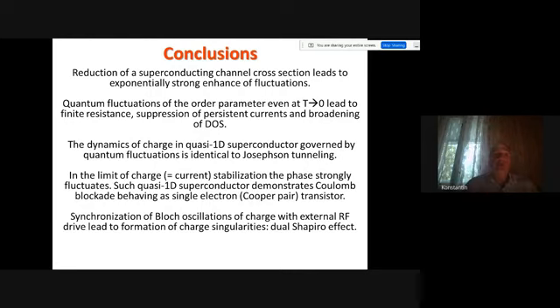So I'm now coming to the conclusions. What I wanted to tell you is that reduction of a superconducting cross-section turns it into a quasi-one-dimensional regime. And it appears that in this limit, the properties of a superconductor depend exponentially strongly on fluctuations. So for sufficiently narrow superconductors, these quantum fluctuations are capable of suppressing zero resistance, suppressing persistent currents, and broadening the density of states. So it's not anymore the BCS density of states.